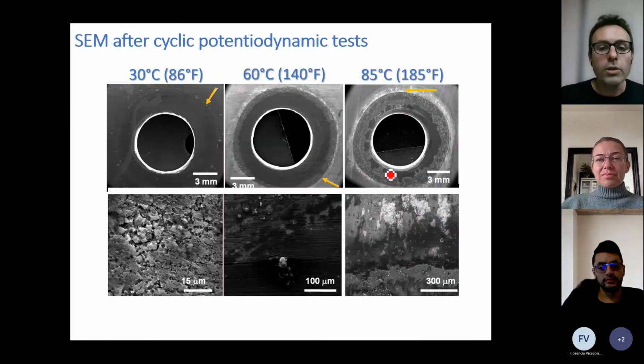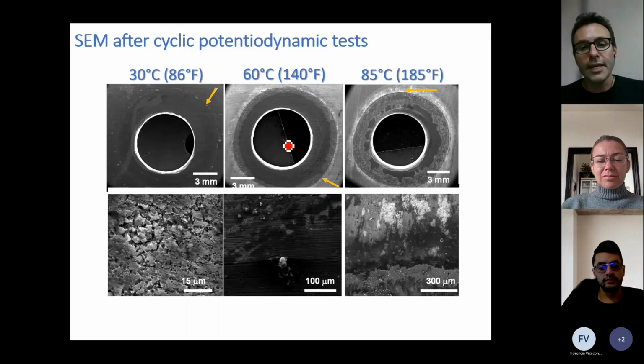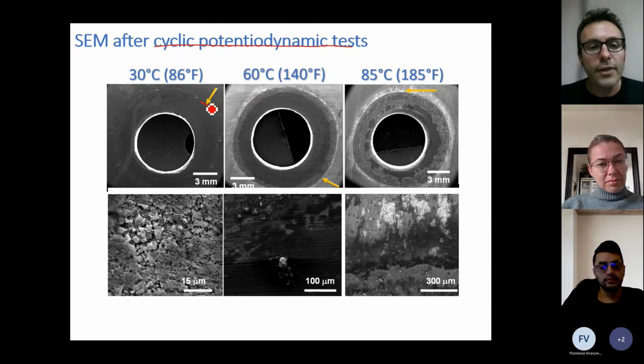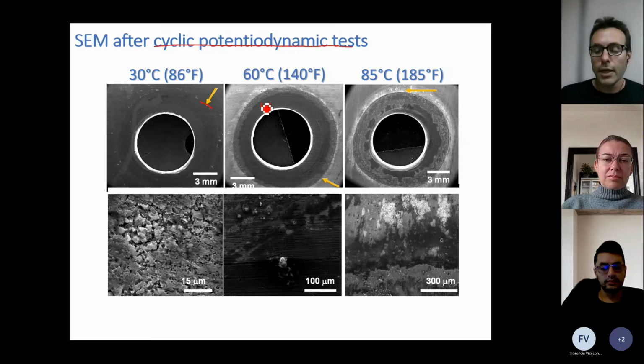So when we looked at the samples in the scanning electron microscope, what we saw is what we see in the figures here at 30, 60, and 85 Celsius. After a cyclic potentiodynamic test, which is a very harsh test, right, where you are polarizing your sample at a very high potential, what we see is initiation, but just at the boundary between the end of the crevice and the environment. So we didn't see any very big localized attack underneath the crevice, which was again good news for us.